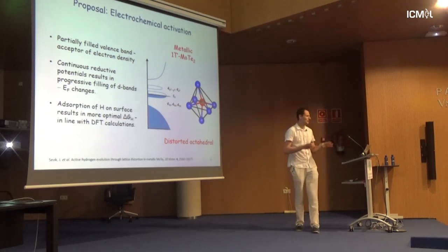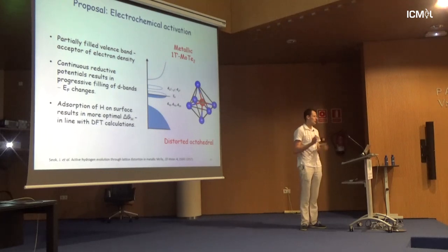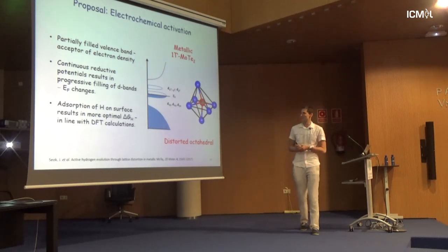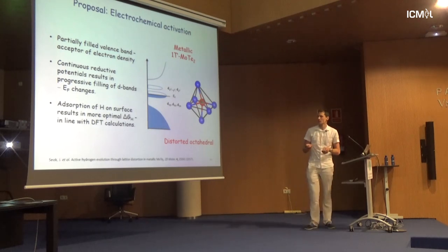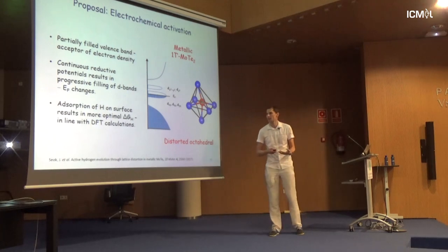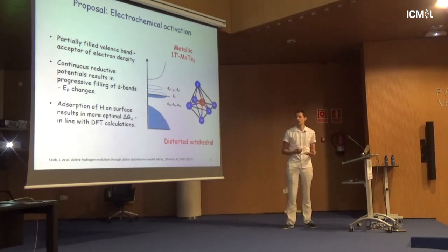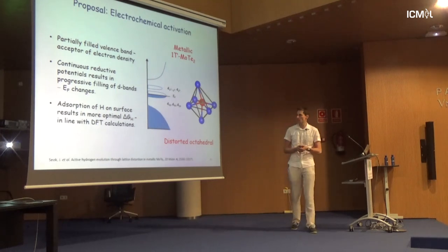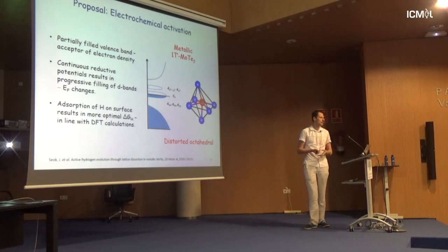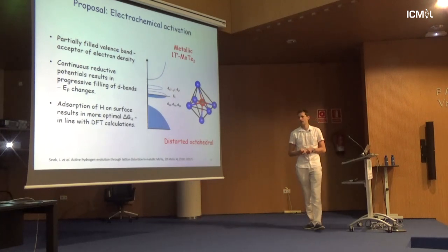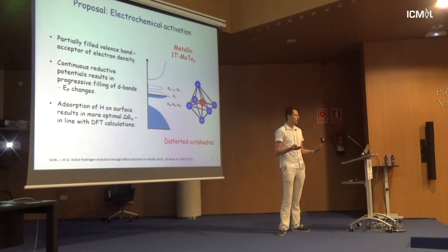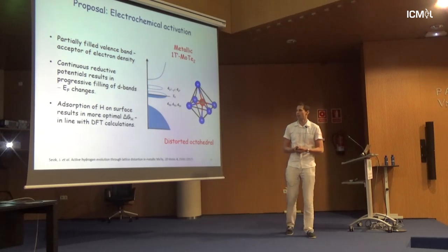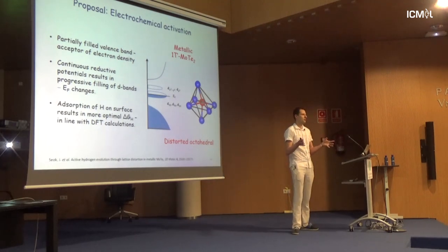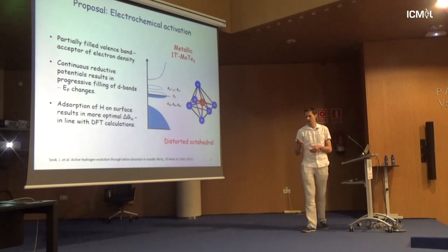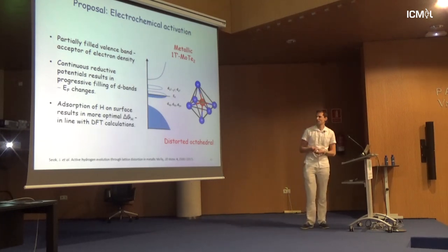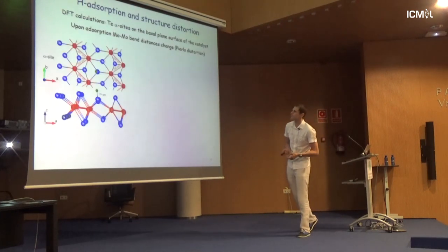So this is the proposal. We have reviewers sort of happy at the moment, so we are just brushing it up at first. So our speculation is that adsorption of hydrogen on the surface also results in optimization of the crystal structure. So we are lifting up a little bit the Fermi level. So this is a lot of work in progress. We have synchrotron time for EXAFS measurements. So we will have in situ measurements, we will do and see what's going to happen. So we will do a lot of in situ and in operando measurements.